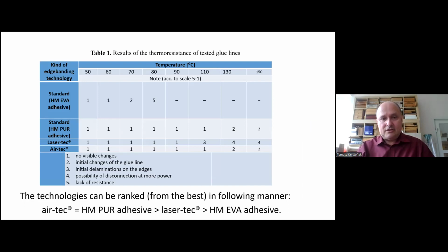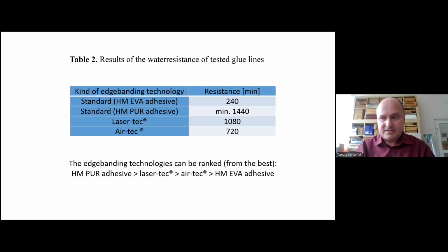Thermoresistance is not good if we use a temperature of more than 100 Celsius. But we need to remember that in our kitchen, we do not use temperatures higher than 100. And you can see the scale, no visible changes. And we cannot see changes up to 90 or 110 Celsius, and the standard adhesive, after using temperature 80, you can see lack of resistance. And it is why using this technology is very good.